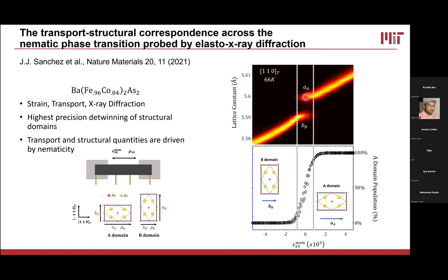So what I see is that in a small strain range where I'm just detwinning the sample, I'm not actually changing the values of the lattice constants. So you could imagine that if the lattice constants were very soft, as I apply strain, I'm partially detwinning, but I'm also partially deforming the domains and changing the lattice constants. But luckily, that's not what happens here. So that gives us confidence that we can apply enough strain to just barely detwin the sample without doing additional lattice constant changes, because those additional changes would induce other anisotropies in the system that we don't want if we want to study the spontaneous anisotropies within a single perfectly detwinned domain. Okay.